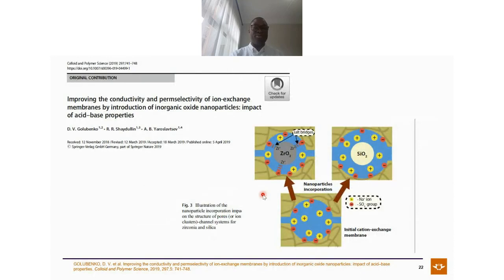Well, we're not the first people or the only people who've reported this type of mechanism. This is the work which was done by Golubenko in Russia. They were also looking at how nanomaterial affects the ion exchange membrane. They also reported the same thing: this is the normal material, and the moment you add nanomaterial, for example, here they're adding zirconium oxide, it's able to align the pathway within your ion exchange membrane. You add SiO2, it's able to also align. This will lead to better ion exchange capacity. As you can see, this is random, so your transportation is delayed, whereas the moment you add nanomaterial, it is increased.